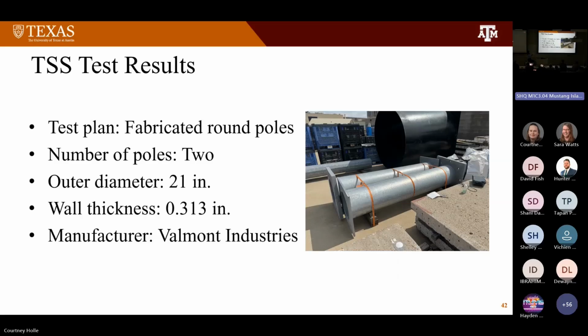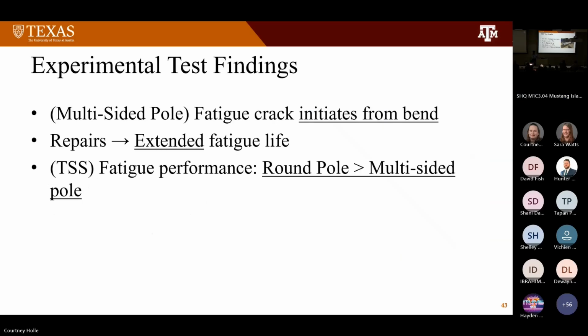After completing the test for those poles, we also wanted to do additional tests for the 2 fabricated round poles as shown on the picture. Their dimensions are shown on the slide. This is what we found from the experimental test so far. We found that the multi-sided pole has fatigue cracks initiated from the bend, and we also confirmed that repair can extend the fatigue life. From the traffic signal poles test, we found that the round pole could have better fatigue performance than the multi-sided pole.